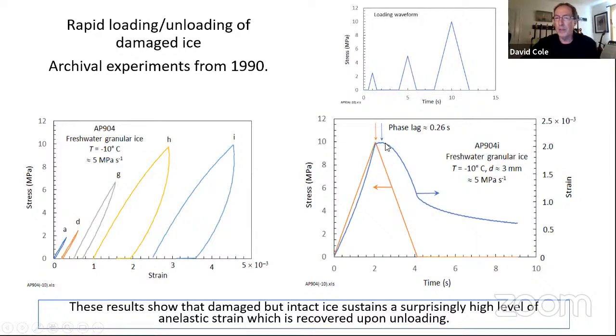But while it's damaged and still intact, and I was very surprised to find this, there's this very large component of anelastic strain that you see basically realized after the load's starting to decrease. The strain hits its peak, in fact, in this case, about a quarter second after the load peak. And this level of strain, which is in the 10 to the minus 3 order of magnitude, is very, very large for this process.